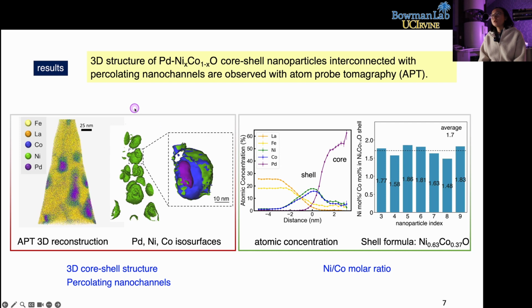In order to check the 3D structure of these palladium, nickel, cobalt exsolved nanoparticles, we use atom probe tomography. With this technique, we can see an interesting 3D reconstruction of the materials and use mass spectroscopy to identify the formulation of the shell part. So this is the APT 3D reconstruction.